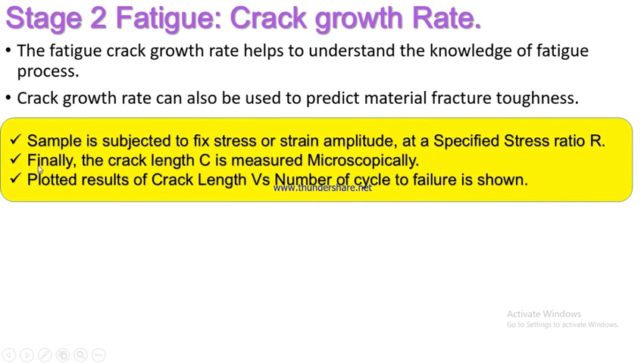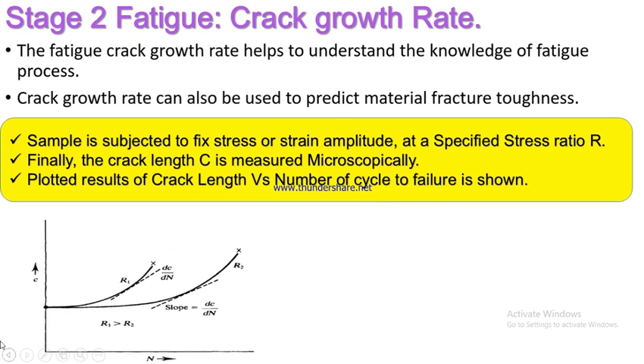So how do we go about this? We say a sample is subjected to a fixed stress or strain amplitude at a specific stress ratio, and finally the crack length, C, is measured microscopically. Then the result is plotted as crack length versus number of stress cycles to failure. This will show the crack growth rate.